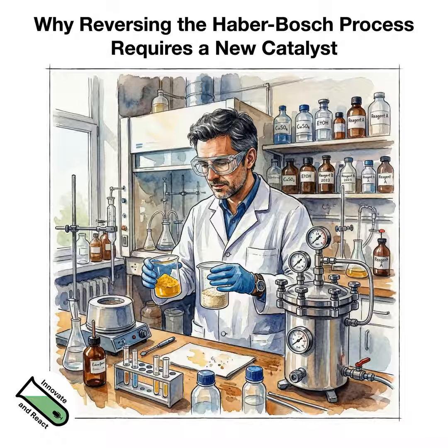Now, what we also looked at, with the help of theory, a DFT partner group at KIT, the group of Felix Studt, is the reaction mechanism of ammonia decomposition in what we call a Langmuir-Hinshelwood mechanism: you adsorb the reactants, they react in their adsorbed state at the surface, and you desorb the products again. And if you compare an iron metal surface and an iron nitride surface, you will find out that the iron nitride is less active.